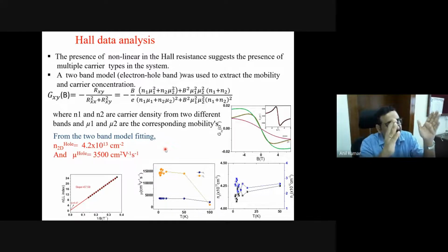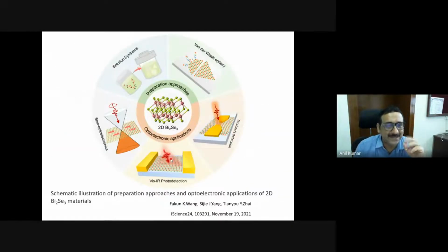So we started with a system which is a weak topological insulator. Theory as well as ARPES data told us that it's a weak topological insulator. Then we looked at the magnetotransport data, and we found that it is a topological insulator. And then we started doping with antimony. Then we could establish pi Berry phase, which is characteristic of these topological systems, as well as we could enhance the mobility of this material to such a high value. So this is a very, very interesting system. Now the question is, what next?